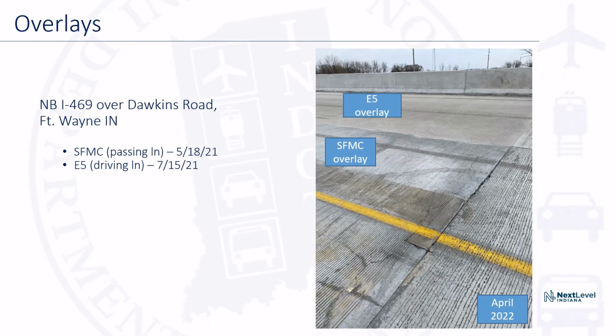Here's I-469 northbound overlay. We've got the E5 overlay. We actually did 2 different types on half the bridge. The E5 was on the top part, and then silica fume was on the bottom, and you could see there the silica fume had cracks that started right away, whereas the E5 did not.